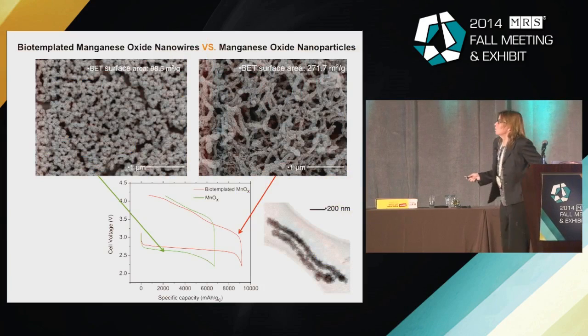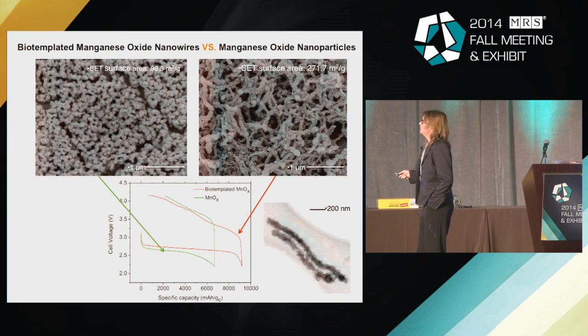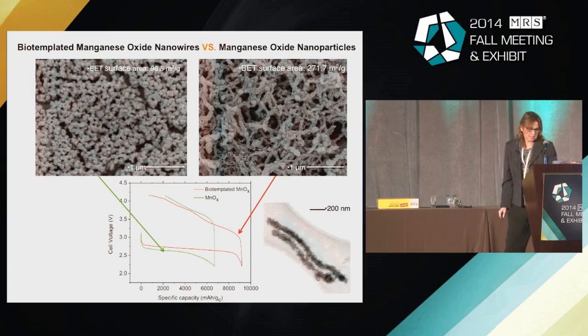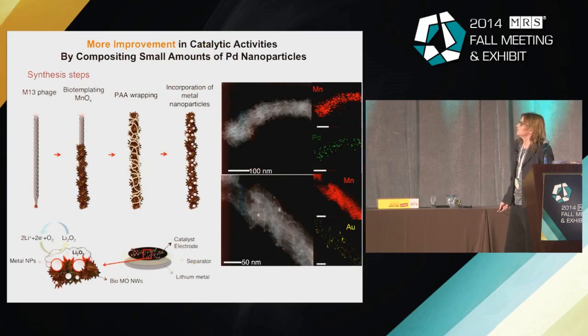And so why is this? Well, one of the reasons is when you get these viruses to form in these wires, they also have these spiky materials, the spiky manganese oxide material, and it forms this porous network, and you have increased surface area. And so we think it makes it easier to have the manganese oxide and the palladium surface interact with the ions in solution and allow for the reversibility of the lithium peroxide.